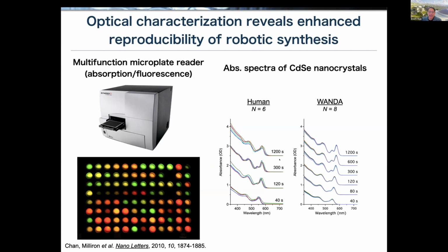So you can see that at a given time point, the spectra for the manually synthesized nanoparticles are fairly scattered because we don't have good control over the reaction. Whereas when we do these reactions in Wanda, at a given time point at 1200 seconds, you see that there looks like there's only one spectrum, but it's actually 8 spectra stacked on top of each other. So that means the nanoparticles that we made are exactly the same. And we didn't even normalize these arbitrarily. We normalized them only by the mass of the aliquots, as I showed you in the previous video.